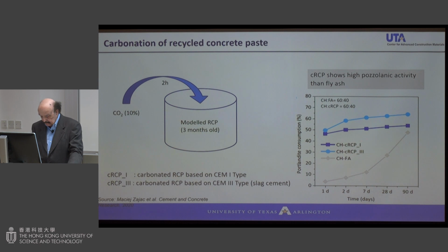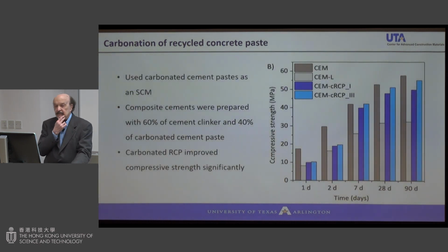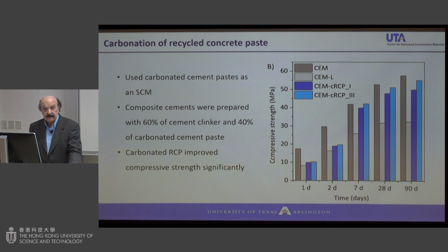So then, one more example of this. This is work done on carbonation at Poly. No, this continues with the cement paste. I'm sorry, this is the Hunan work. I remember I told you that we often try to replace cement with limestone. But if you replace cement with limestone without any pozzolanic material, obviously you reduce the strength. But now, in addition to limestone, we have added recycled paste. Just look at these: control, addition of limestone, and limestone plus recycled paste. And you have increased compressive strength quite a bit because of the pozzolanic activity.